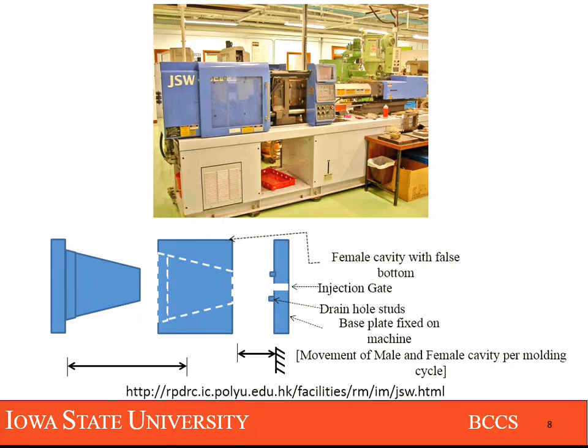So once we got all of these resins, we took them down to some of our partner molding houses in Missouri, Kansas City. Initially, especially like what Jim mentioned earlier, with the high protein content plastics, we had to come up with a way of demolding them without breaking them, because the green strength of these materials was not that great, nothing compared to polyethylene or even low density polyethylene.